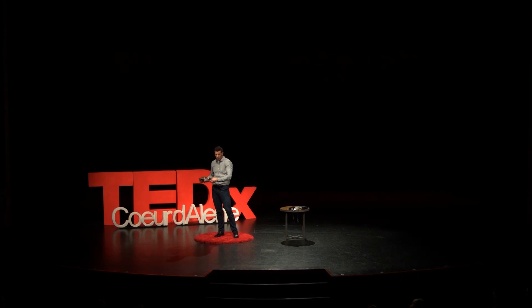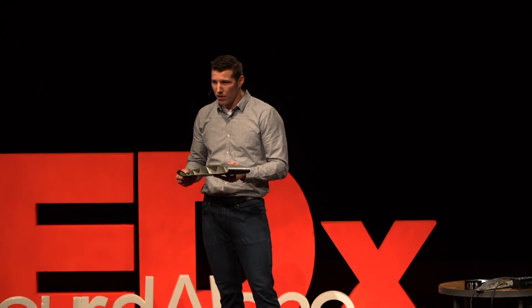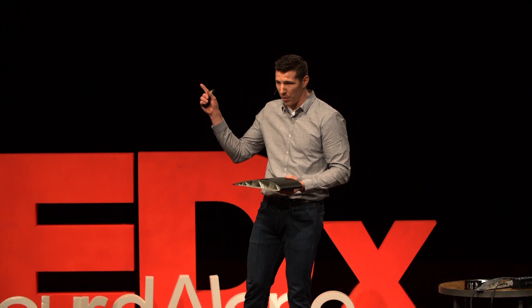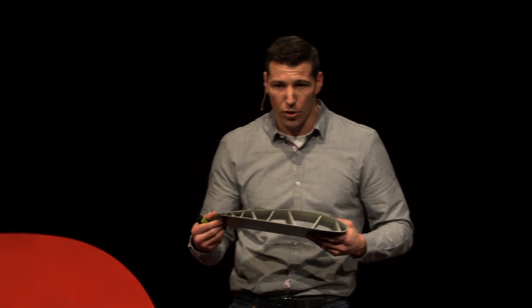Now that you have this really costly material on rolls, you lay it out on a flat surface and cut shapes out similar to a cookie cutter. All of the leftover material after removing those shapes is scrap — there's upwards of 30% material waste when building with composite materials. Then you take those shapes, lay them over the mold, and that mold with the prepreg material is inserted into an autoclave, essentially a massive pressure cooker that applies pressure to consolidate the material and heat to cure the resin. To manufacture a commercial airplane wing, you'd need an autoclave the size of the wing itself.